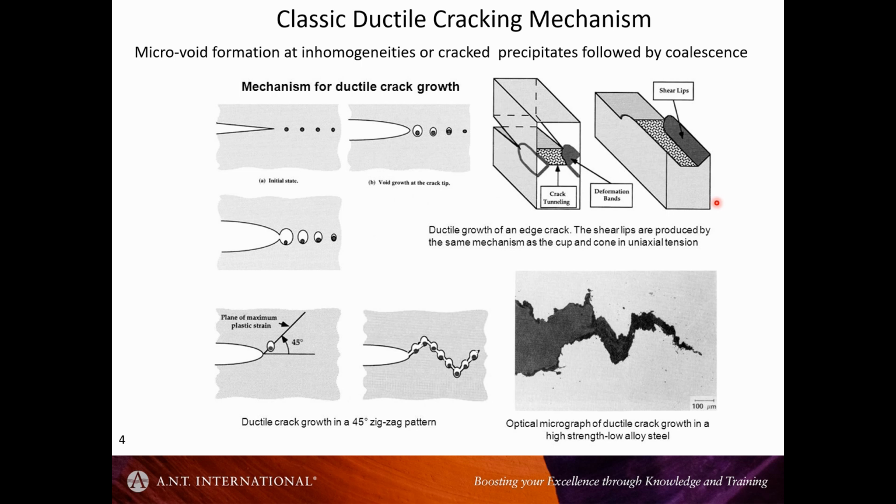the material is constrained. So what you tend to get, if it's a thick specimen, let's say a tensile specimen, is preferential failure at 45 degrees, which is known as the plane stress condition, but in the center you've got constraints, and it's under what's known as plane strain deformation.